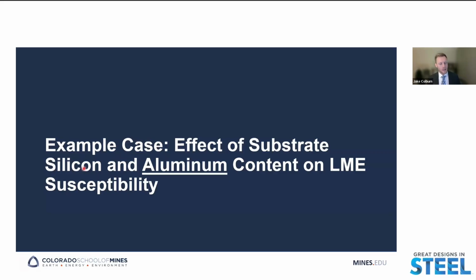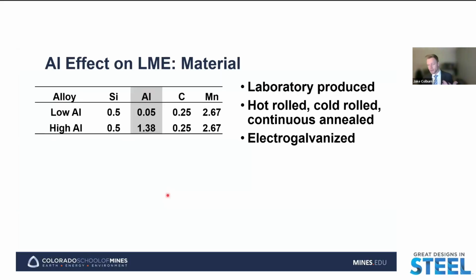So that's specifically looking at silicon, but now we can take a look at the effect of aluminum content on LME susceptibility. The main reason we want to do that is that, again, as an alloying addition, if we want to keep the silicon concentration lower so as to not increase the LME susceptibility, we can then substitute some of that carbide suppression and solid solution strengthening effect of silicon with aluminum. And so here again, we have two alloys that we're going to be comparing that have equal compositions of silicon, carbon, and manganese, and we're changing the aluminum concentration from our low value at 0.05 weight percent to the high aluminum alloy, which is 1.38 weight percent aluminum. These two alloys were also produced in the same way as the previous ones: laboratory produced, hot rolled, cold rolled, went through continuous annealing simulations, and then were electrogalvanized with a pure zinc coating.